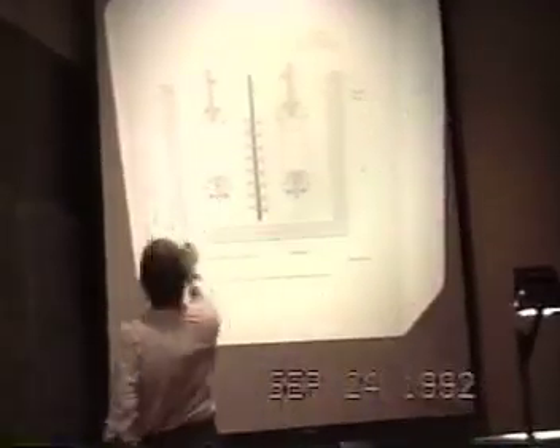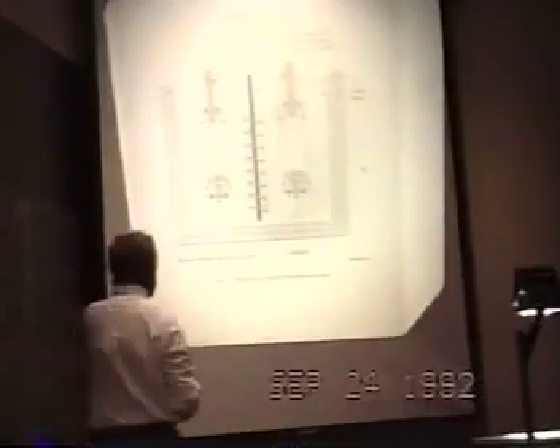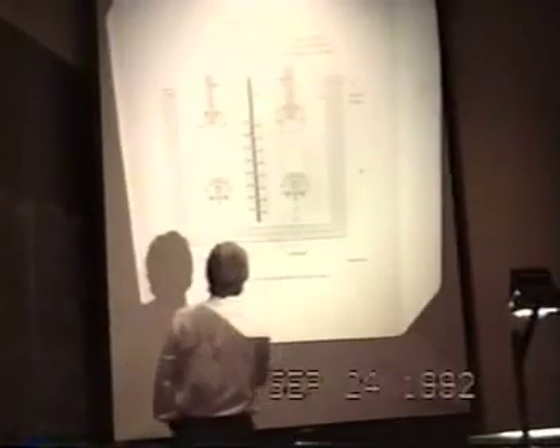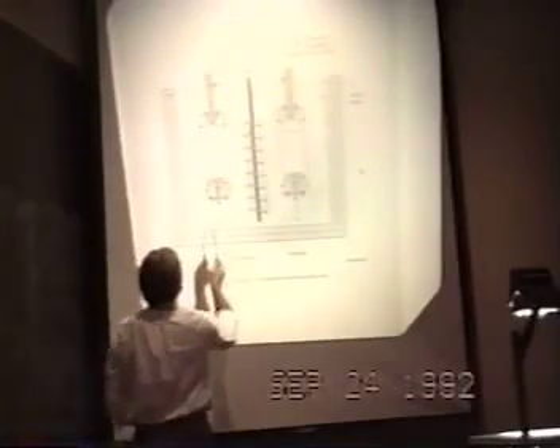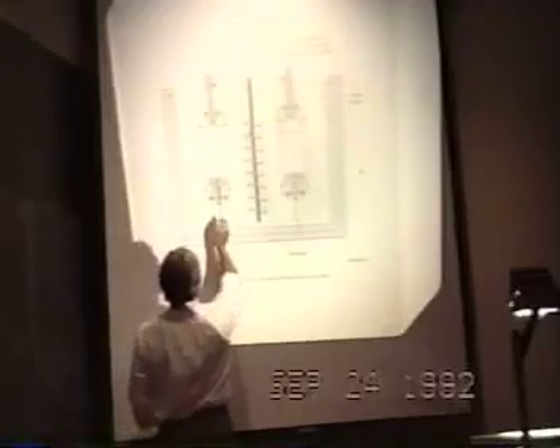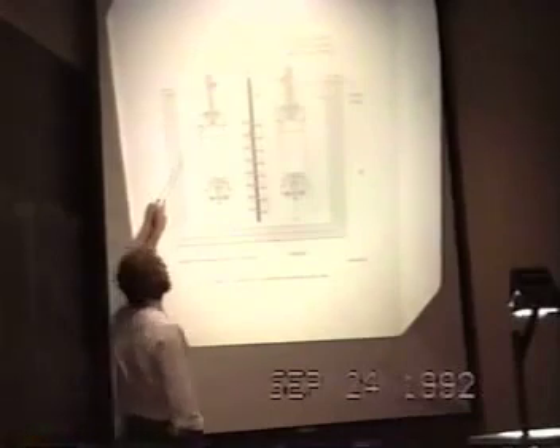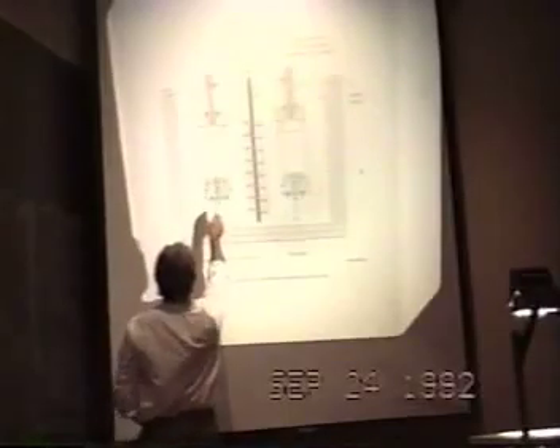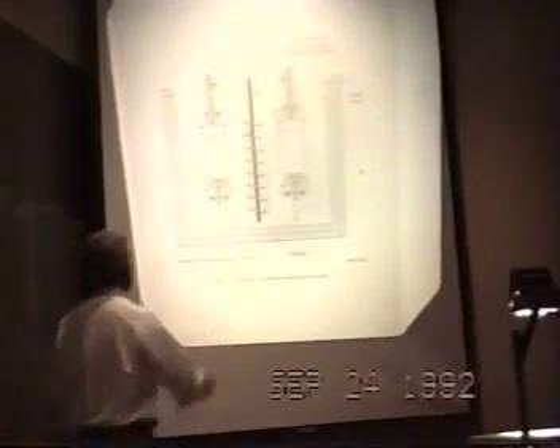If we look at this thing in profile, seeing 2 calorimeters, and with this dimension now of the order of a meter, 2 flow calorimeters side by side, suspended above the bottom of the well-stirred bath. The flow is drawn from the bath, past 2 inlet temperature sensors, past the electrochemical cell which is placed in this environment, out past 2 outlet temperature sensors, platinum resistance temperature devices, RTDs, and in many of the experiments that I'll describe, also 2 thermistors were placed in that volume and pumped by a constant flow rate pump.